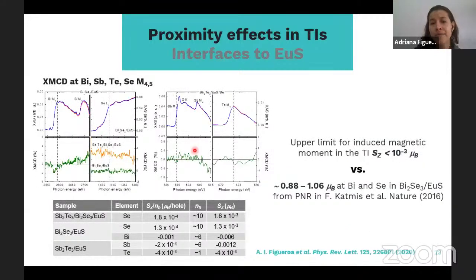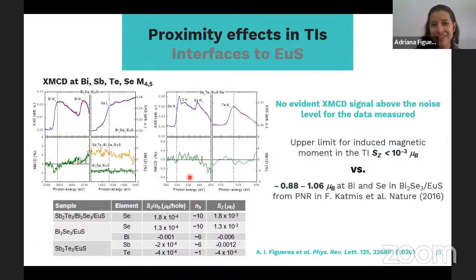And then finally, we are interested in what happens magnetically at the TI, right? That is one of the nice things about XMCD, that you can tune the energy to explore the magnetic order and magnetic character of the atoms in the TI layer. So we tuned the energy to the bismuth, antimony, tellurium, and selenium atoms of our TI layers. And then we basically found no evident XMCD signal. It is quite noisy, and we found no XMCD signal above the noise level of the data measured.